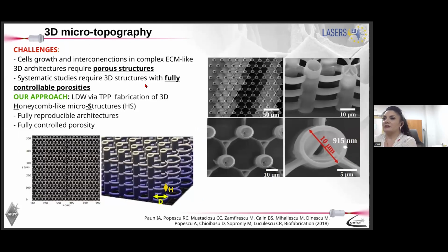As such, in the following study, we managed to fabricate, with the same printing technique, a honeycomb-like structure made of vertical microtubes and separating layers with different distances between them. So what we managed to do here is to fully control the structure's porosity. And we want to see what porosity is the best to host osteoblast-like cells and what porosity is the best to support these cells to form bone tissue.